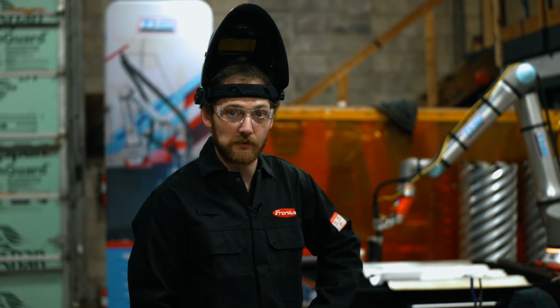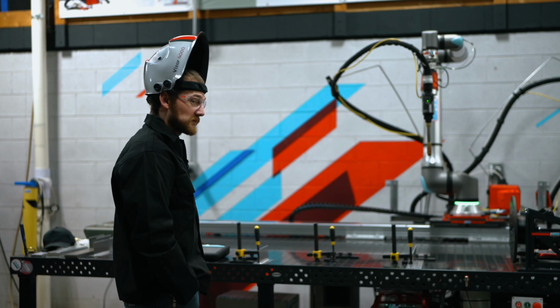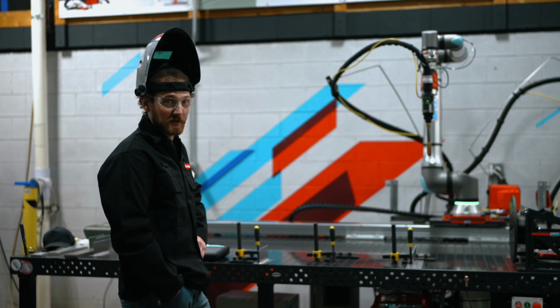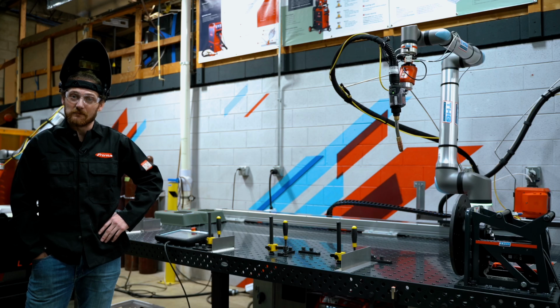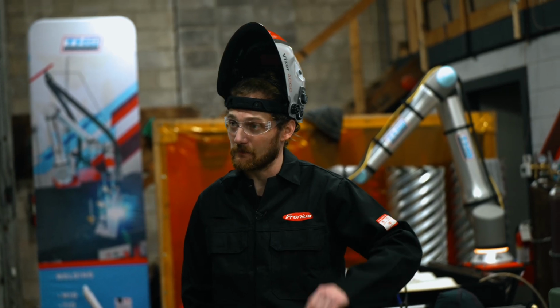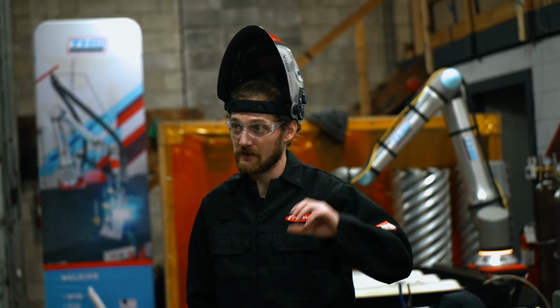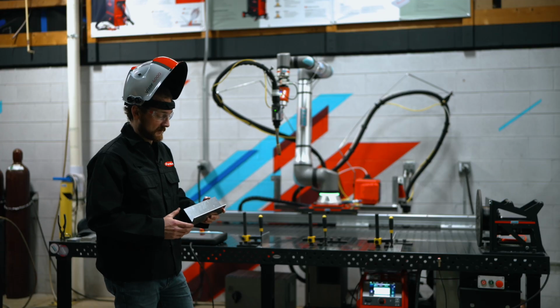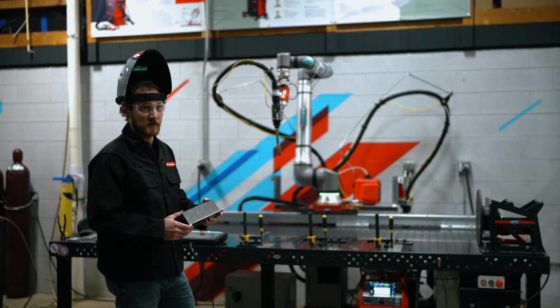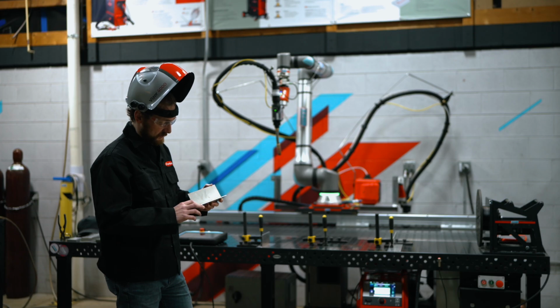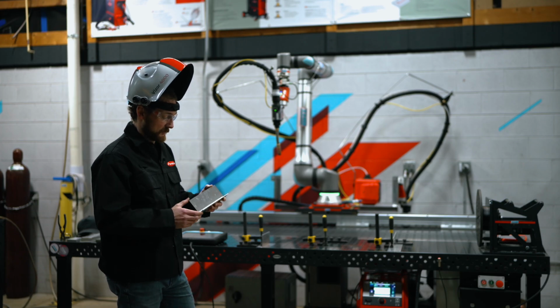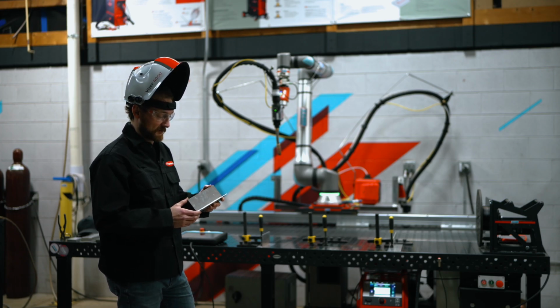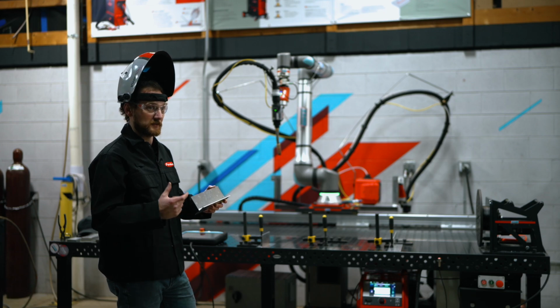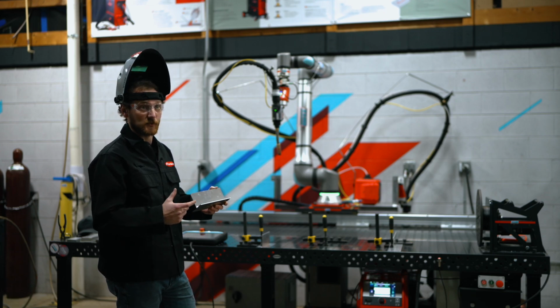Either vertical or overhead positions, which are typically not something you see with other equipment. A standard pulse trying to run vertical up would struggle and drop out, whereas a mix process allows that puddle to solidify before you advance your travel speed. In this last example, we're using CMT mix, and you can see that the spacing on the solidification line is tight, which can be fine depending on application, but if you're looking more of an aesthetic with the stack of dimes more spaced out,